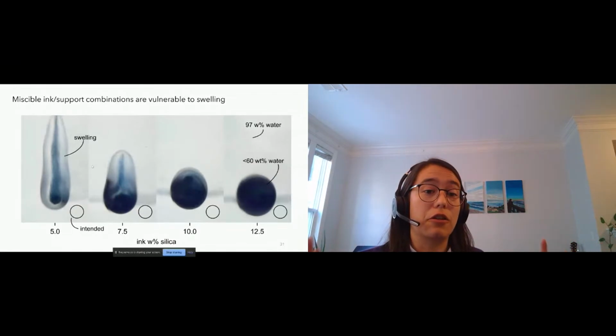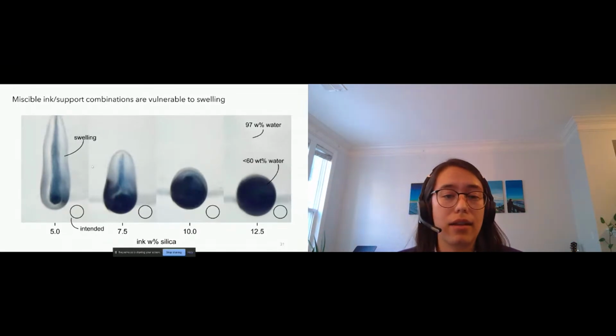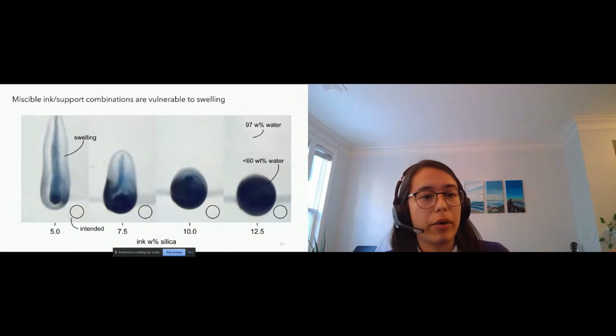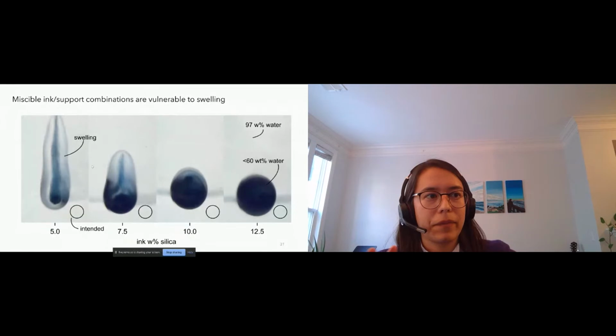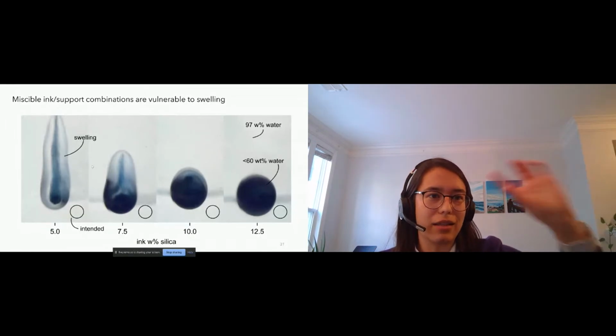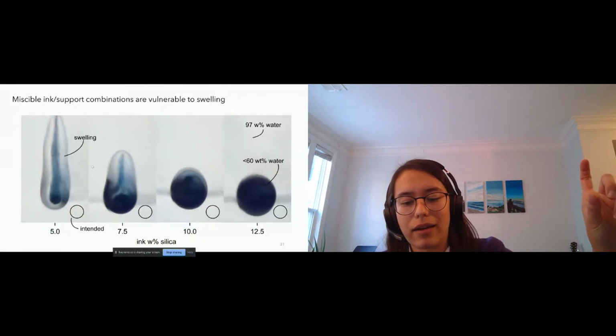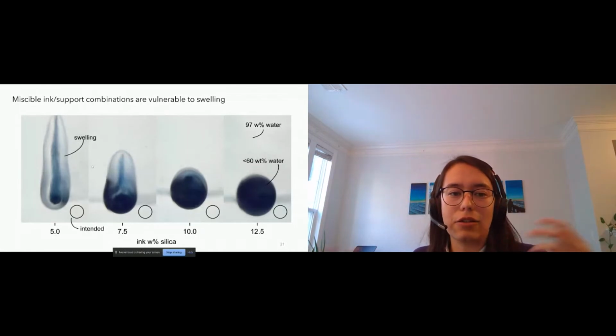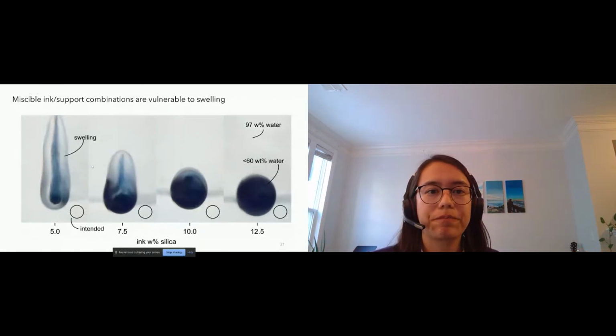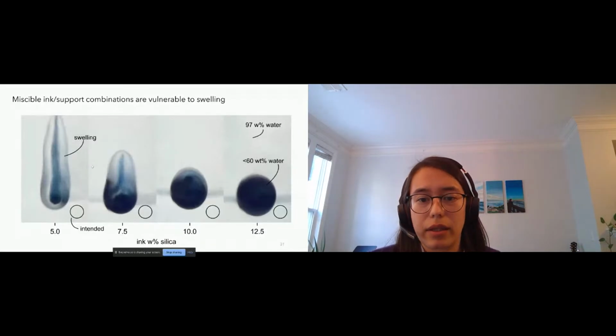the filament to swell. And that's going to cause a lot of problems because as you're printing your part, the filaments that you've already printed are going to be swelling, and you're going to be printing new filament that is smaller. And so you get a lot of geometric inaccuracies, and you could end up with problems with fusion. So suppressing that swelling is really important.